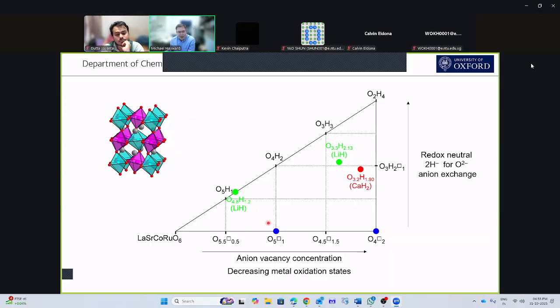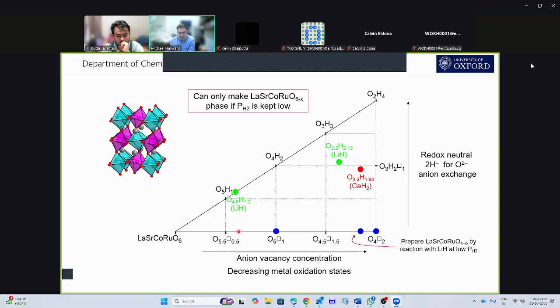So the point we're going to make here is we can only make these oxygen deficient phases without the hydrogen in if we keep the partial pressure of hydrogen low. And actually we can see these are intermediates in the reaction to make the oxyhydride, because what I can do is we can prepare a sample which hasn't completely done the reaction. So we can make a sample which is, say, 4.2 with hydride and with vacancies. And then if I seal that material in the presence of lithium hydride, it will then convert to the oxyhydride, showing that this is an intermediate.